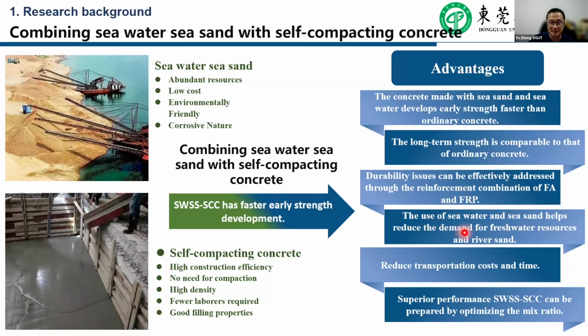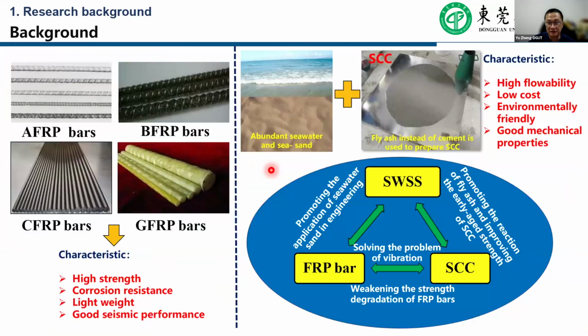Using seawater and sea sand can help to reduce the demand for freshwater resources and river sand. Furthermore, we also reduce the transportation costs. And finally, the behavior of the seawater and sea sand self-compacting concrete is better than that of the traditional self-compacting concrete. Therefore, we try to combine those materials together. It has been evident that using FRP as the replacement of the steel reinforcement is an effective way to solve steel reinforcement corrosion. And therefore, based on the FRP material properties, seawater and sea sand can be used in the concrete production.